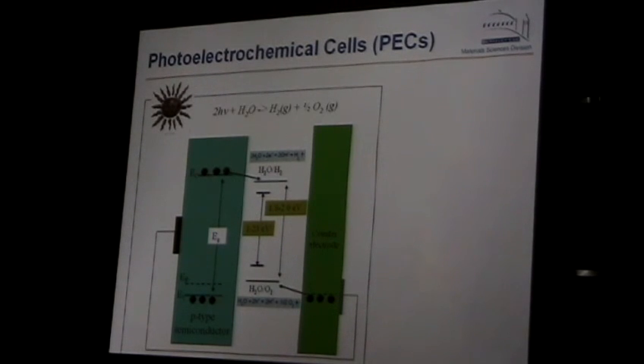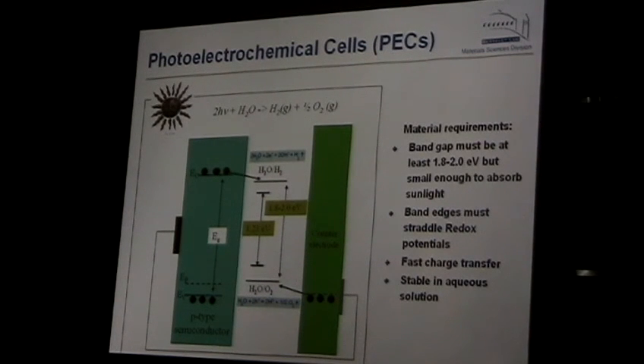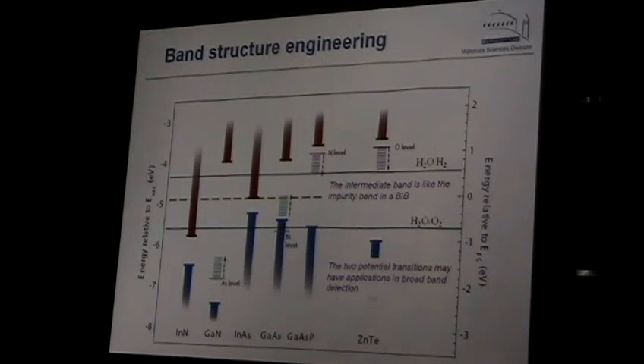And so, of course, in our case, we claim we can manipulate the conduction band edge, we can move the conduction band edge, we can move the valence band edge. So we can engineer properties of semiconductor to hopefully fit this. And if you look at some of the semiconductors which could be manipulated this way, so again, these are hydrogen and oxygen redox potential. So we want to have conduction band above, but not too far, because if the gap is too large, there is no light absorbed, and that's useless as well.